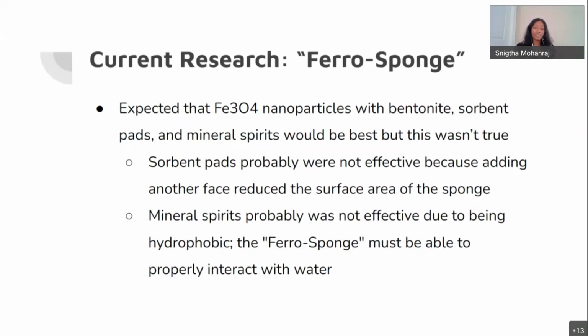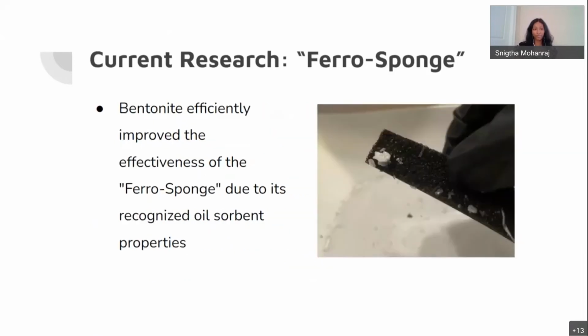This was most likely because the sorbent pads actually reduced the net surface area of the sponge because it added another face. And this probably limited how much of the microplastics were able to be removed since it limited the area available for that. The mineral spirits probably were not very effective since they have a hydrophobic nature. And since the ferrosponge is treating water, it has to interact properly with it. But the hydrophobic nature of the mineral spirits would repel that water and prevent that from happening.